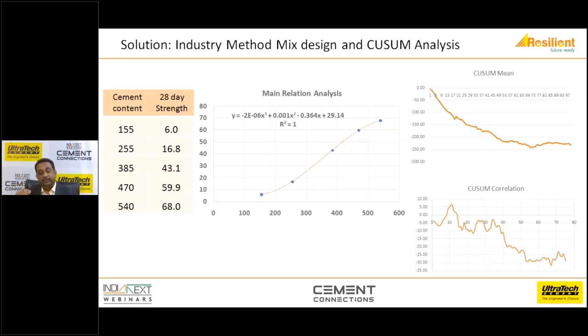The sum of the deviation, which is the cumulative sum of the deviation, is the CUSUM analysis by which you pick up the trend. Once you pick up the trend, here you have the CUSUM mean, which tells you whether the strength is going down or going up. Based on this, you need to actually adjust your cement content.